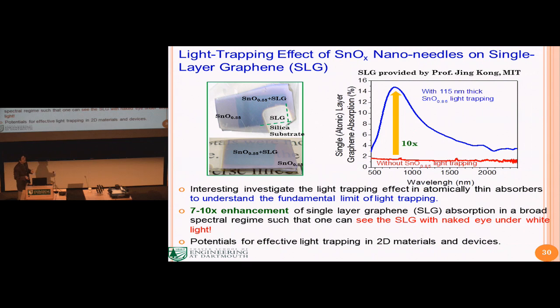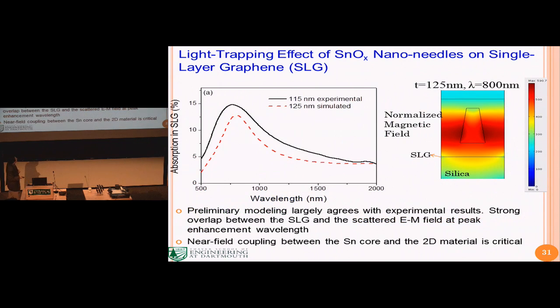So can we understand it by optical simulations? Well, we just started to do this work. It seems there are a lot of tricky things here, but we can get a general agreement with the experimental results. So this is the calculation. This black curve is experimental. And it seems that the field enhancement near this single layer graphene is very important to enhance the absorption. You can see this is not the optimal case because the highest field is still near the tin core. So if we further engineer the structure, we should be able to get even stronger enhancement here.